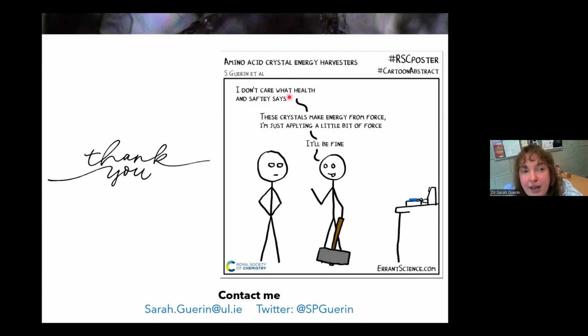Efficiency is a hard one. Really, it's about fatigue testing, it's about cycling, it's about repeated application of force over time. You can get the single crystal efficiency from measuring your electromechanical coupling coefficient, which you can get from impedance analysis. So that's a K squared, and that gives you a rough idea of the electromechanical conversion efficiency inherent to your material. But for the macro scale applications, I think it's just normal cycling and fatigue testing to see what the material can withstand mechanically.